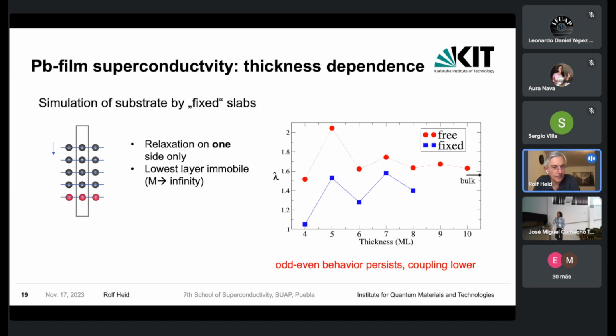Now, why it's decreasing? Essentially, you're taking out a little bit of a degree of freedom here, of course, because you make the lowest layer immobile. The idea to make that immobile is actually to simulate a kind of stronger binding of the lower layer to the substrate. And typically, this binding takes away a certain degrees of freedom, which then contribute to the superconducting pairing, and that then reduces these coupling constants. So it has an effect on all kinds of properties. The position and the effect of the quantum well state is slightly changed, but you change to a larger extent, of course, the phonon spectrum here. So all these ingredients are contributing, and also the electron-phonon coupling of the lower layer is then completely taken out here.